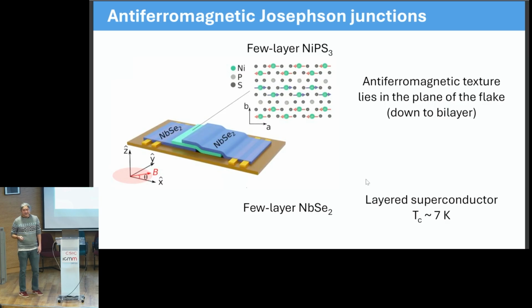As an antiferromagnet, what we use here is this material NiPS₃. And why this material? Well, this is an antiferromagnet that has the antiferromagnetic texture in the plane of the layered material. So this means we can actually transfer this antiferromagnetic texture to a device. Many antiferromagnetic layered materials actually have the antiferromagnetic coupling from layer to layer. So this wouldn't allow us to test this kind of texture on the superconductivity. We did this then with NiPS₃, which is also a lot more stable than the ferromagnetic materials we tried before. The samples were prepared in inert atmosphere.